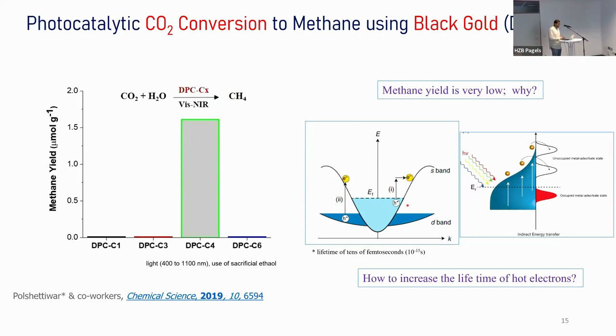And we came up with the idea that, okay, this is the gold, say the blue color part is the gold. You generate the hot electrons here, and then you add another nanoparticle connected to the gold, which has empty orbitals, empty states. Say in this case, we choose nickel, because nickel is known as a good catalyst for thermal CO2 reduction. That's why we chose nickel.